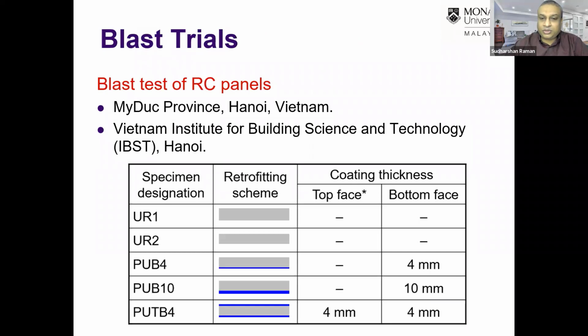And then the same material we applied as a coating for reinforced concrete panels under blast loads. These tests were conducted in the MyDuc Province in Hanoi, Vietnam, where we tested about 4 panels. The first panel had a slightly different dimension, and then UR2, unreinforced 2, was a bare panel without any coating. PUB4, PUB10, and PUTB4 represent different coating thickness and coating location.